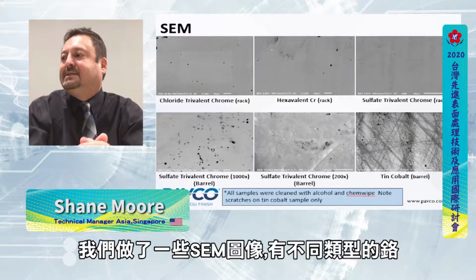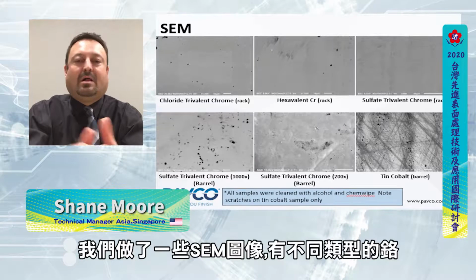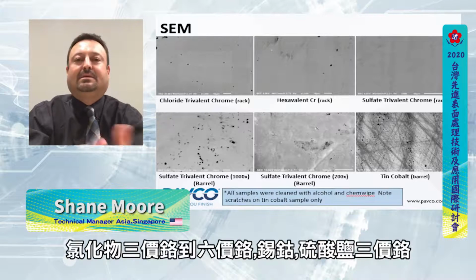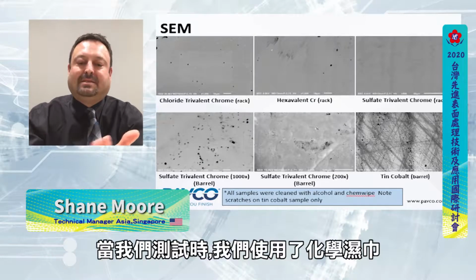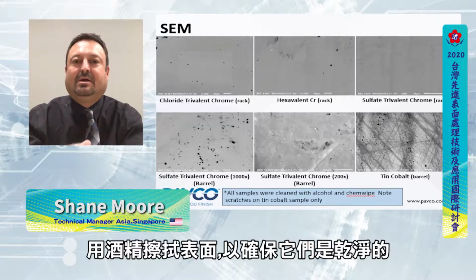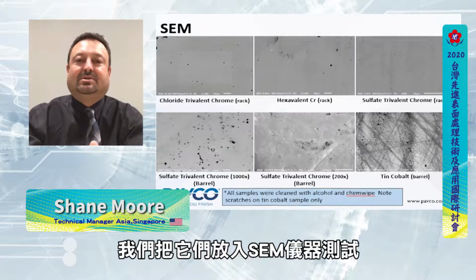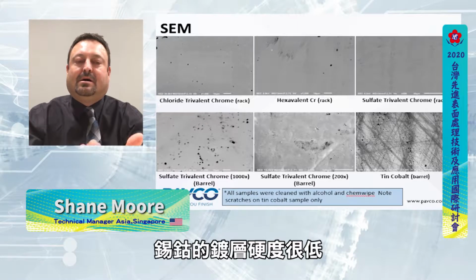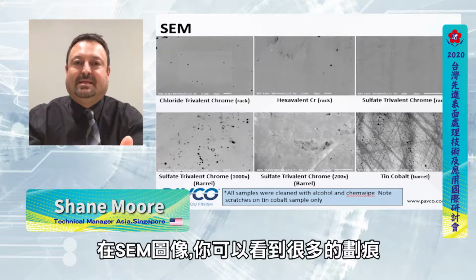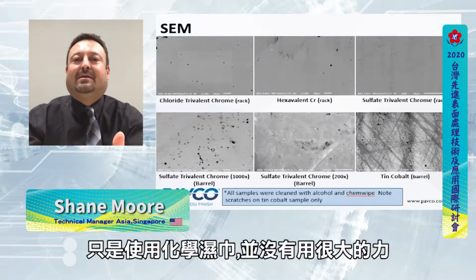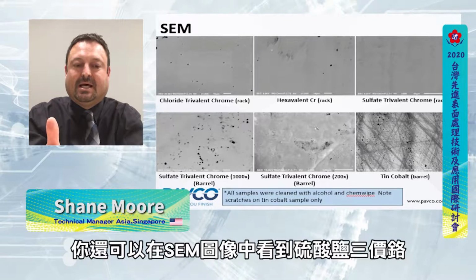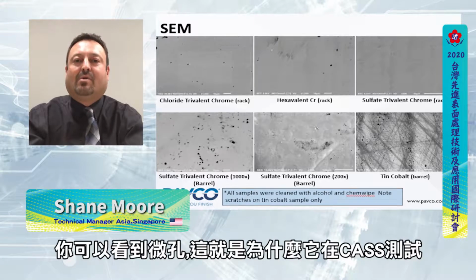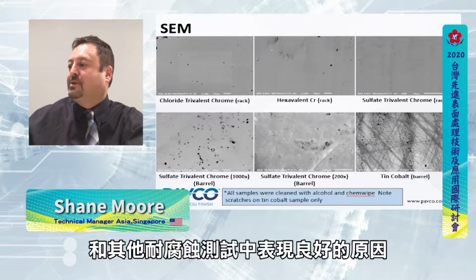We did some SEM images on all of the different types of chromium: the chloride-based, hexavalent, tin cobalt, and sulfate-based. We took some chem wipes and wiped them with alcohol to make sure that they were clean before we put them into the SEM instrument. With tin cobalt, the deposit was so soft that in the SEM images you can actually see all the scratches that came about just from using that chem wipe, which is not very aggressive. You can also see in the SEM images that the sulfate-based has really visible micro porosity, and that's why it does so well in cabinets and other corrosion-resistant systems.